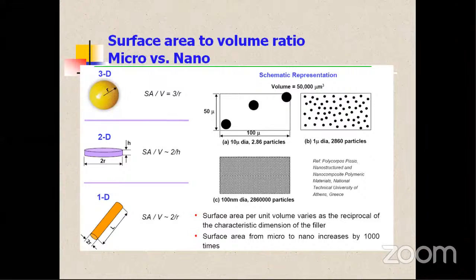So instead of ductility, the brittleness is increased for this. Whereas the same particles, around 2860 particles of 1 micron, if you further go for synthesis of those particles, so that each particle after synthesis is at nano level, like 100 nanometer, then see the number of particles, for the same weight you took for A, B or C, because of the reduction in size from micro to nano.